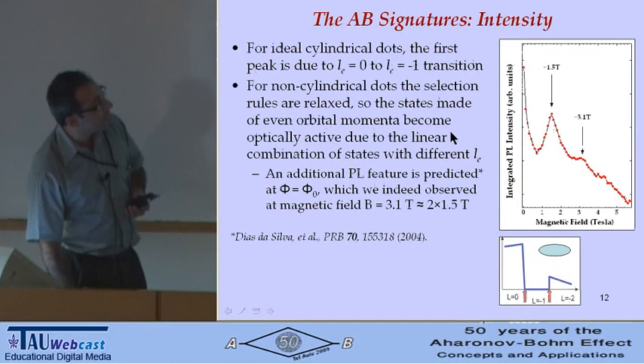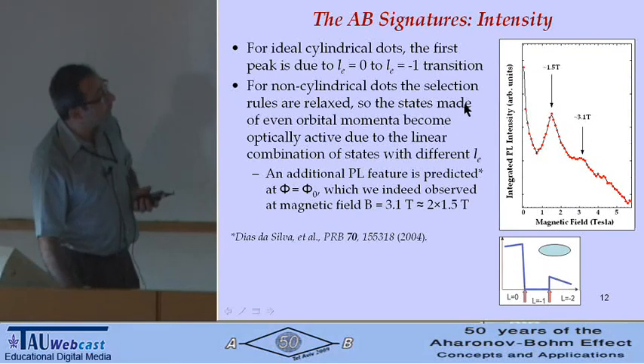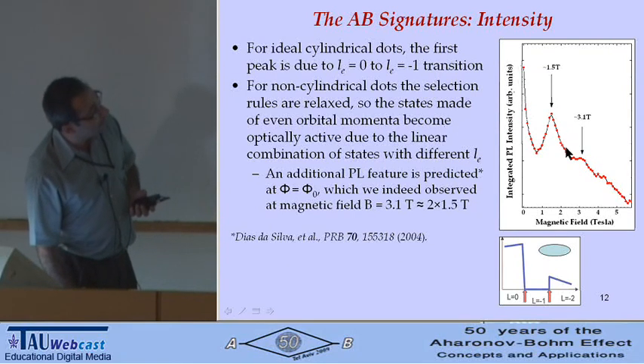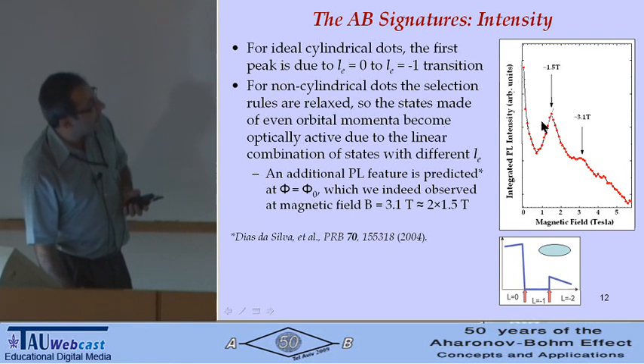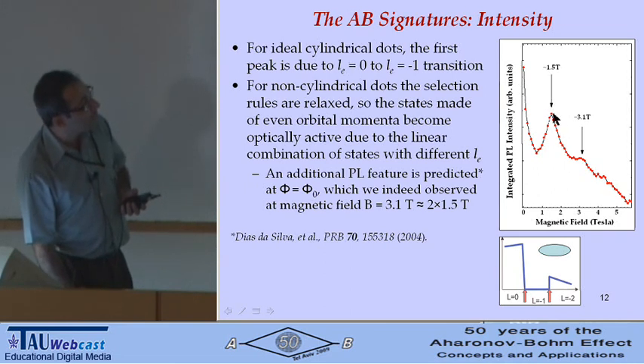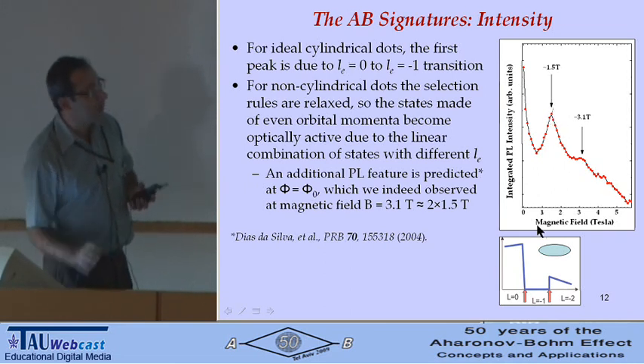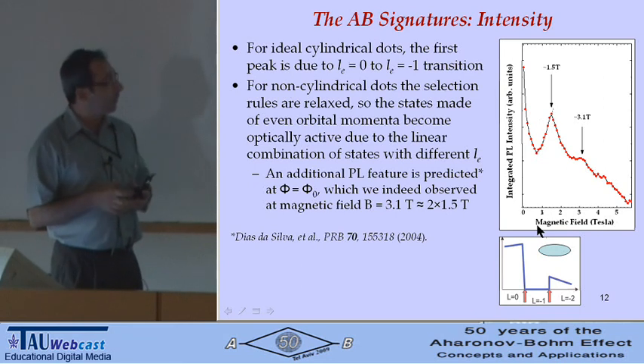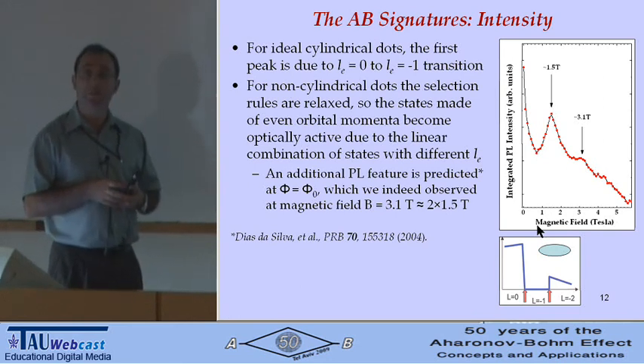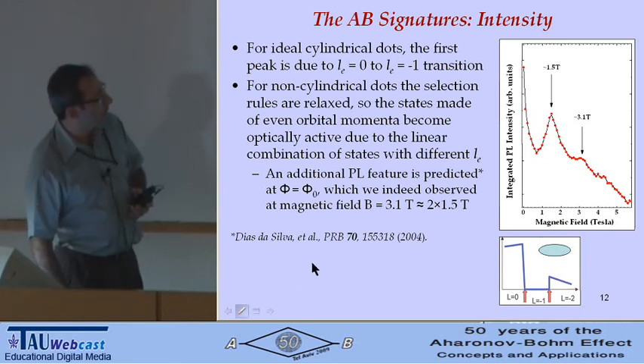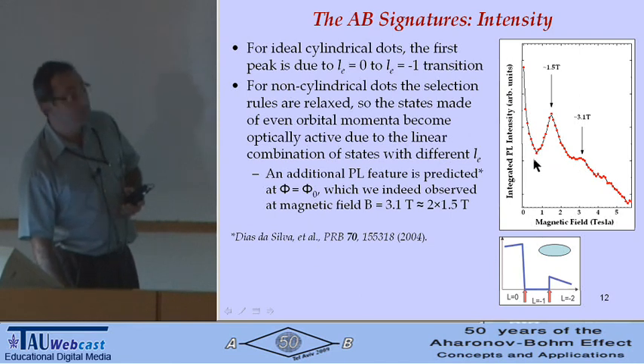So I'll show you here in a little bit more detail one of the samples, where you can see very nice oscillation. And this happens at phi 0/2. And because the system is not symmetrical, you can show that another feature has to appear at exactly twice the magnetic field, and we do see it.